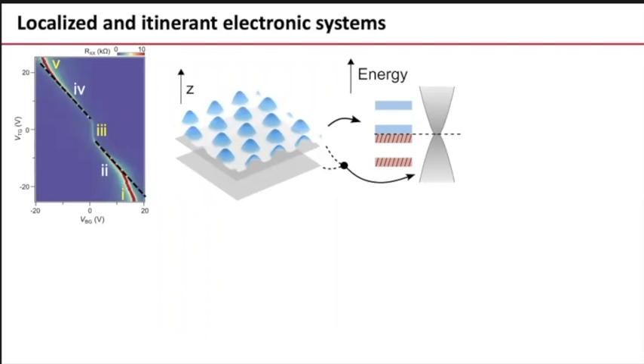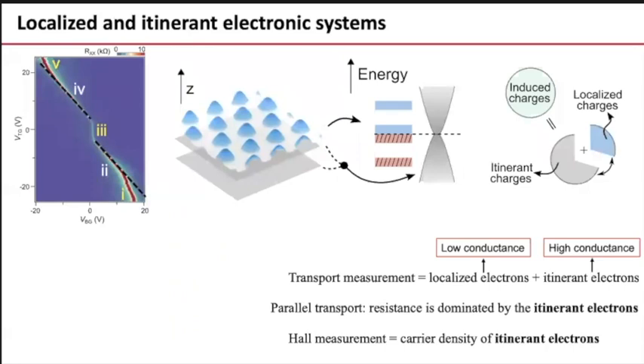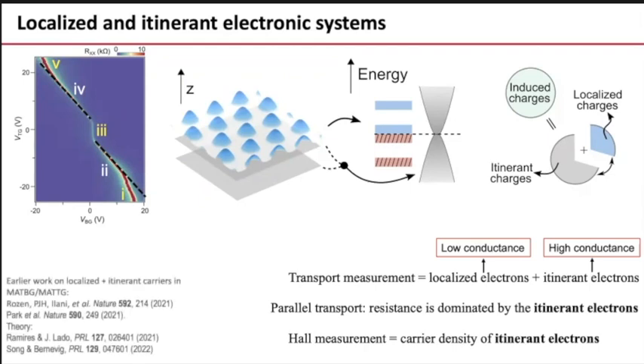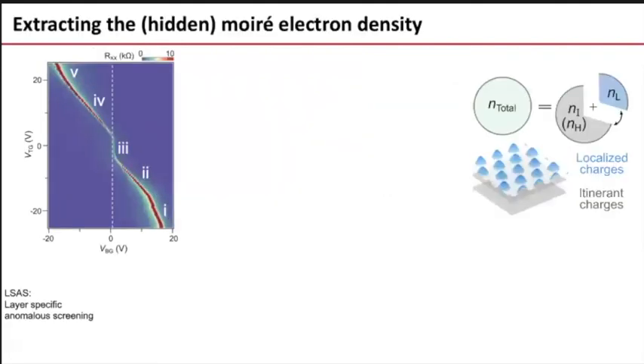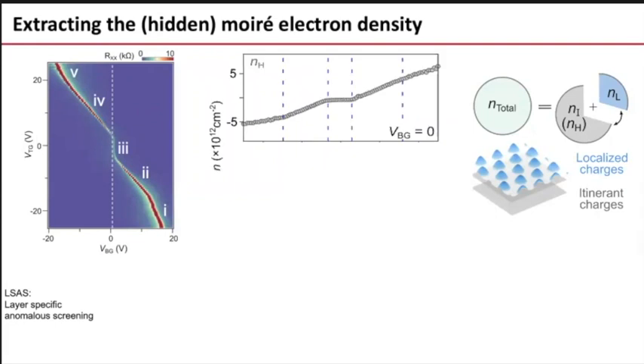Regular bilayer graphene-like. Okay? So in your electronic system now, there seem to be these two populations of carriers. When you measure transport, you are only looking at what happens with the itinerant electrons. Okay? The localized electrons don't contribute to transport. So even if something is happening in the localized electrons, you don't see it, because in transport, you only measure the thing that is moving, okay? If you do Hall measurements, the same thing, okay? The carrier density is telling you about the itinerant electrons, not about the localized electrons. But let me show you what type of interplay happens between the localized and the itinerant electrons. And by the way, again, this notion that there are localized Hubbard-like electrons has been proposed by many people. So one thing that we can do is we can measure the hole density, okay, along this trace here, this white dash trace.